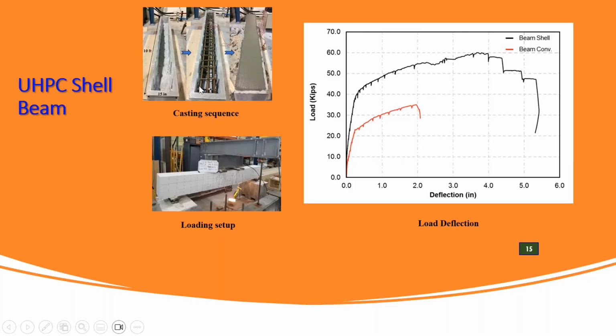And as I was saying, even the very small amount of UHPC shell that you're providing adds significantly. What you are seeing in this diagram are two curves. These are the load deflection curves of two beams. The red one is a rectangular beam that is made entirely with normal strength concrete. The black line is the load deflection curve for a beam that has a UHPC shell and is then filled with regular concrete. Both beams have exactly the same dimensions, except the black one has a UHPC shell, so a certain part of it is made of UHPC, and it becomes a permanent part of the finished structure. As you can see here, that adds significantly to the strength. See how much strength you gain by basically replacing a formwork with a UHPC shell that becomes a permanent part of the structure.